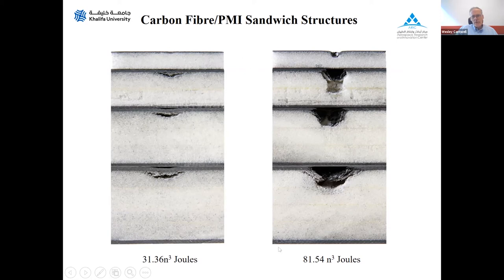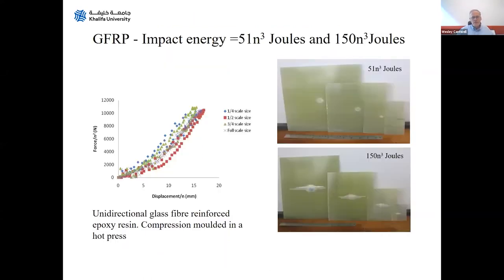It's perhaps clearer if we look at the higher impact energy where the indenter starts to penetrate the core, and you can see here the quarter scale, and compare that to the full scale sample. This one's subjected to almost 82 joules, and this one to a little over 31 joules, but both subjected to the same scaled energy. So damage patterns and failure mechanisms appear to be similar across all the scale sizes, and the approach seems to have some value. So that all looked pretty good.